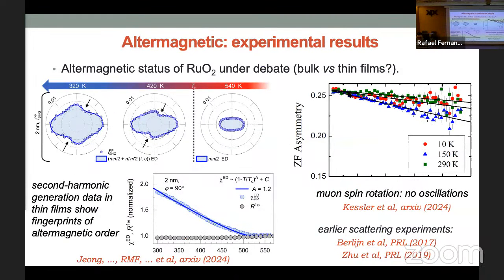Experiments. If you've been following it, you know there is a controversy: is ruthenium oxide an altermagnet? The real question is, is ruthenium oxide magnetic or not? Manganese difluoride, there's no question. Ruthenium oxide is a bit different. I'm just going to tell you what has been discussed here. These papers are very recent. This paper goes back to early scattering experiments a few years ago, where they saw a magnetic moment in ruthenium oxide. There's a very recent paper by this group saying that they don't see anything. This is muon spin rotation, and they also do neutron scattering.